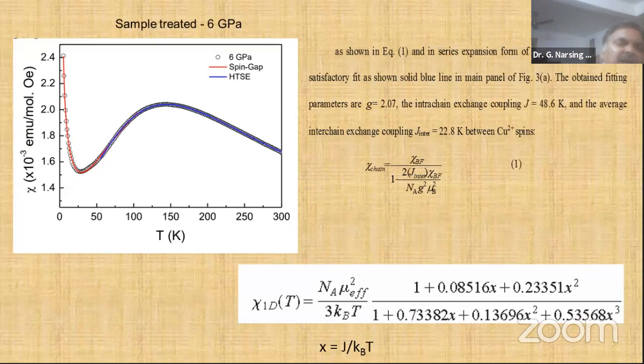So we got behavior like this, and one can identify which type of behavior it is. Normally we would say it's antiferromagnetic because it's going down. But it's not antiferromagnetic. If it were an antiferromagnet, when you differentiate this there should be a maximum or minimum. Here there will be smooth increasing or smooth decreasing, with no anomaly in dχ/dT. That means there is no long range ordering. Long range ordering means 3D. Three-dimensional magnetic ordering is not there in this sample.